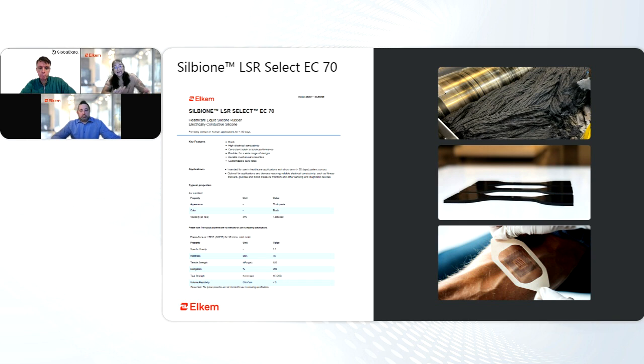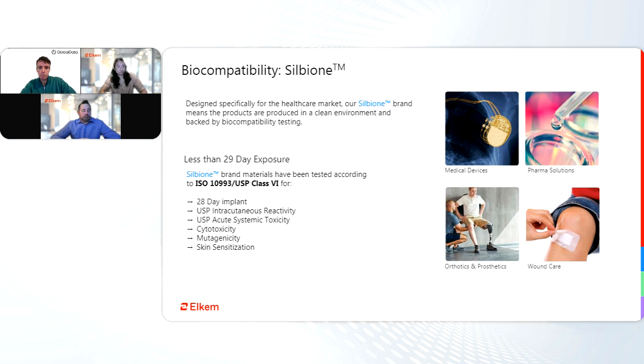The durometer is set at 70 Shore A with tensile strength of around 920 psi, elongation at 250%, and a 45 ppi tear strength. The most important property for this product is the volume resistivity, which is consistently measuring out to be at around less than 5 ohms centimeter.